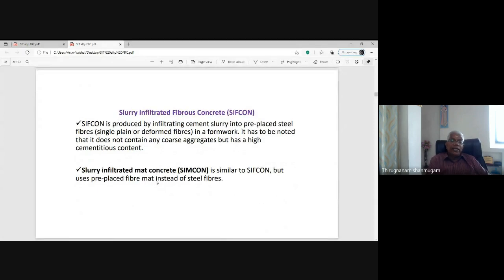Slurry infiltrated fibrous concrete, SIFCON, is produced by infiltrating cement slurry into pre-placed steel fibers in a form. It has to be noted that it does not contain any coarse aggregate but has a high cementitious content. So SIFCON is nothing but cement-based slurry infiltrated through a bed of fibers in a formwork. The formwork may be a cube or cylinder or slab or beam or column or foundation, anything. Once the formwork is ready, you sprinkle the fibers to form a fiber bed. After completing the volume of the mold, flowable cement slurry is poured or infiltrated into the formwork. The resulting product is SIFCON.